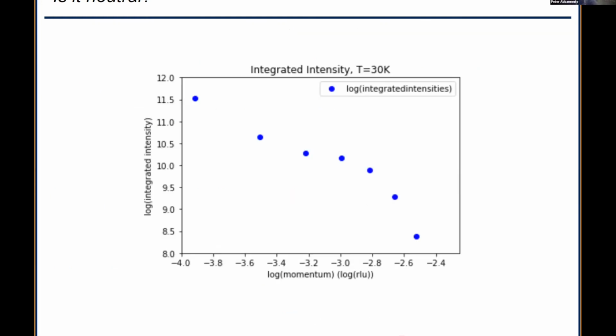Okay, so here's what it looks like. This is the integrated intensity of the mode as a function of Q, and this is on a log-log plot because we're interested in a power law. The first thing you can see is that it doesn't look like a power law at all, which is not surprising. It's not guaranteed to be a power law, but as you go to small momentum, it's possible to ask what power law it is approaching in that limit. I think we have enough data points to at least make a guess.